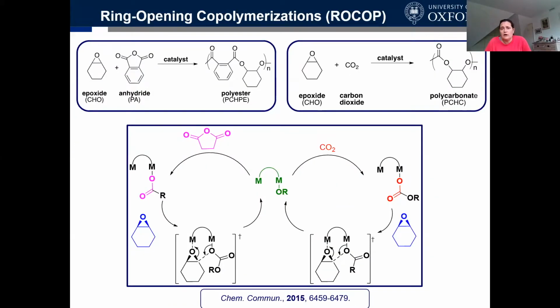These polymers with carbon dioxide in, they work in an alternating copolymerization, and you need a catalyst for that to work. The catalyst has two different types of intermediates in the cycle. One is an alkoxide, and when carbon dioxide inserts into that alkoxide, you form a carbonate. That carbonate then attacks an epoxide and regenerates the alkoxide. So in our slide at the bottom, we're going from the green species in the middle over to the right-hand side and back again.